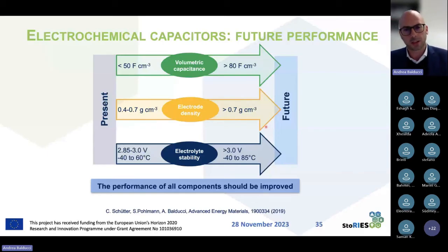So for example, what it will be important to do in the future is to increase the volumetric capacitance, so the farad per cubic centimeter, from lower than 50 nowadays up to 80. The electrode density should be increased. Nowadays, it's between 0.4 and 0.7 gram per cubic centimeter and should go to more than 0.7. And then when we are talking about the electrolyte, what we should try to increase is the electrolyte stability, because with acetonitrile, we are able to reach 3 volts. We should go higher, because we know that the energy goes with the square of the voltage. So the higher the voltage, the higher will be the energy.